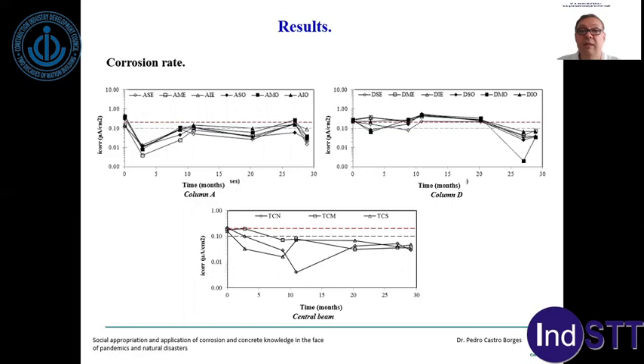So that was very important to us. And the second thing to observe here is that all the tendencies are flat. And that was very important, because the third thing was to note the dotted lines, specifically the red dotted line. That means the threshold between the passivated and the depassivated zones. And in this case, all of the values were below the depassivation zone. So we were not at risk of having corrosion, and the behavior of all the structure was as we were expecting. So that made us feel very, very happy until now. So the durability design was working.